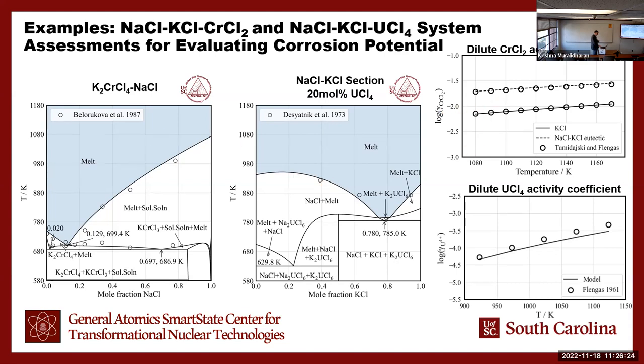The other thing is you want to worry about corrosion. So you need information like what's the chromium chloride activity coefficient. And so here is our model in the lines and the data are circles. Darn good there. And here's the activity coefficient for uranium tetrachloride in the sodium potassium uranium tetrachloride system. Again, we're reproducing data that's available.